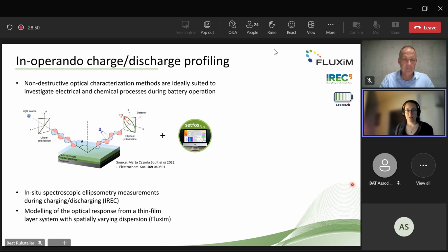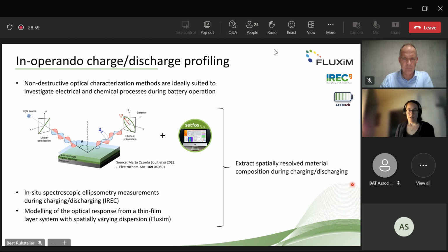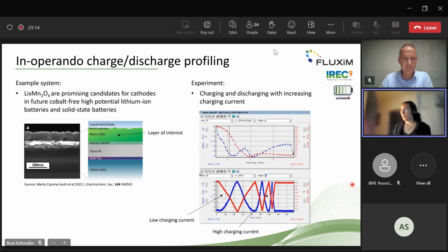And what we did now is to add our simulation software, namely the optical part, and try to reproduce what they measure to get a material composition, ideally spatially resolved. So as a function of the film thickness, we want to understand what the composition of the elements in there is and how they change. The system first was this LMO, which is a promising candidate for cobalt-free lithium-ion batteries. And they just put this on top of, I think, a platinum electrode.